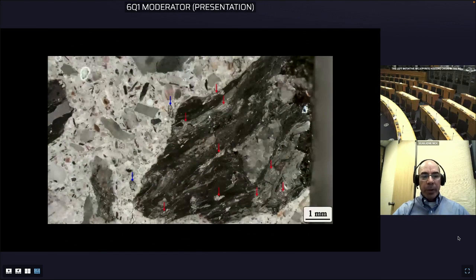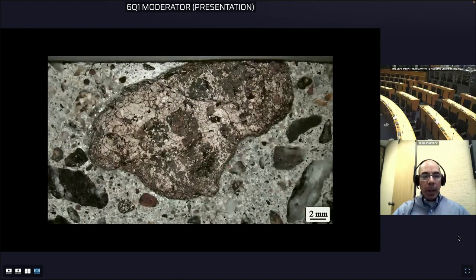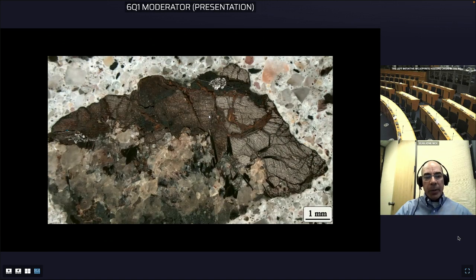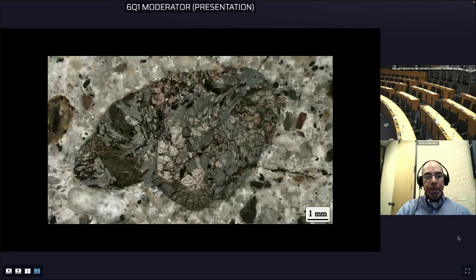Another example with red arrows pointing to the pyrrhotite. This is one of the particles where about 75 percent is pyrrhotite — all that gold color. In the close-up, the pyrrhotite in the interior portion of the particle is still gold and less oxidized, but as you move toward the exterior you can see striations indicating oxidation, and at the very end a darker brown color indicates significant oxidation. Another example with high pyrrhotite also contains graphite as a gray mineral.